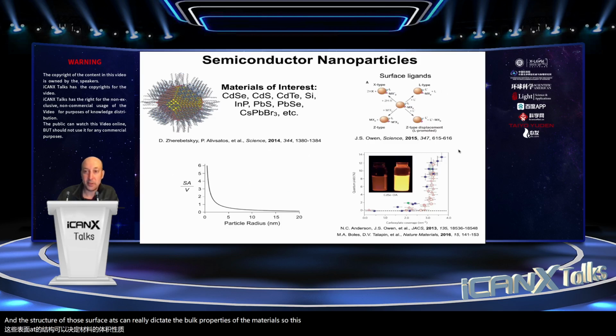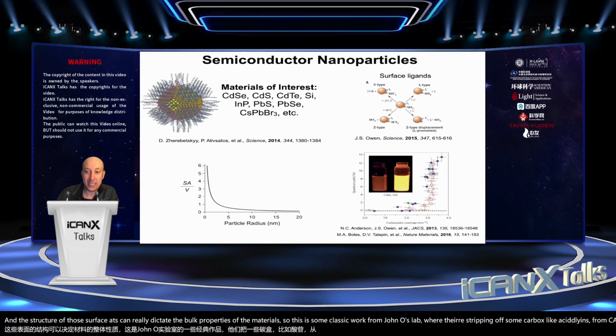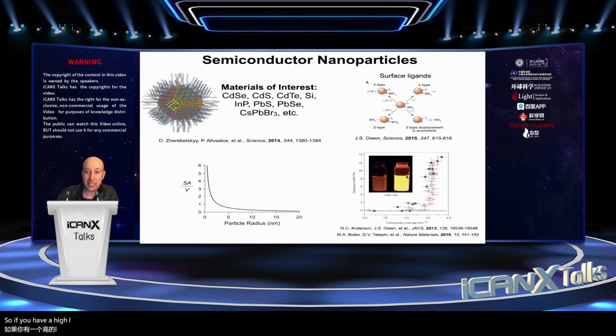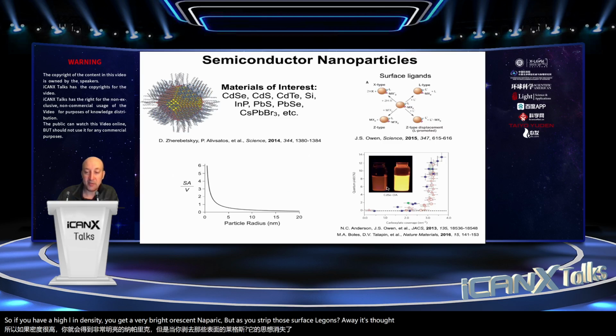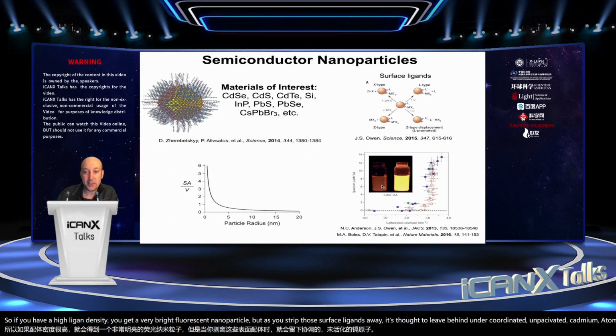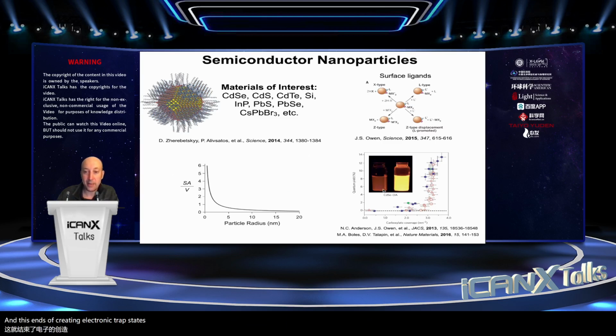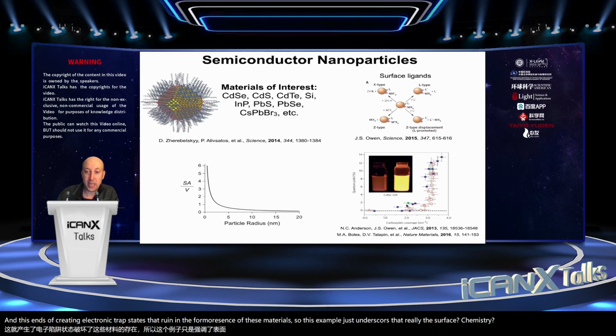So this is some classic work from John Owen's lab, where they're stripping off some carboxylic acid ligands from cadmium selenide. So if you have a high ligand density, you get a very bright fluorescent nanoparticle, but as you strip those surface ligands away, it's thought to leave behind under-coordinated, unpassivated cadmium atoms, and this ends up creating electronic trap states that ruin the fluorescence of these materials. So this example just underscores that really the surface chemistry and surface properties can end up dictating the properties of the bulk material.